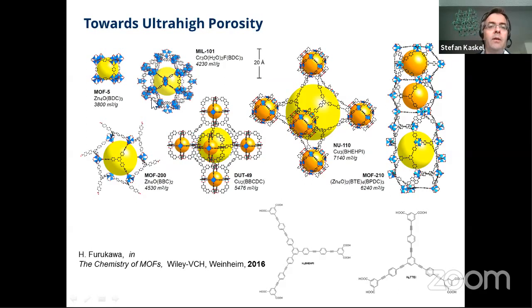And of course, some of the materials from Férey's group and some other MOFs, some of the early MOFs in the field. And you see basically to achieve very high specific surface area, you can identify two principles here. One is making the linker longer and longer, making the struts thinner and thinner is a strategy to achieve higher and higher surface area. Basically to have very thin struts that provide this high accessible surface area. But of course, this is also a very expensive technology and also time consuming to make these very complex linkers.